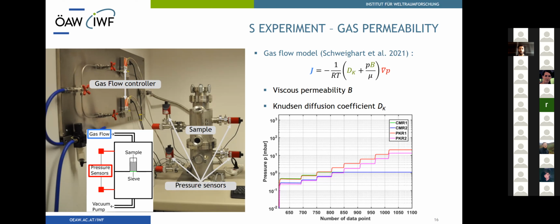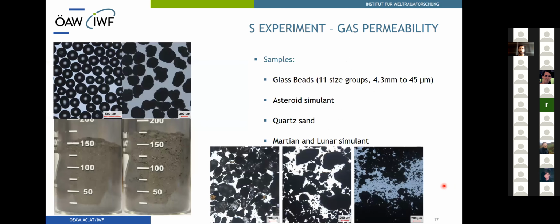In this figure, you can see how we perform the measurements. We increase the gas flow in multiple steps and record the steady state pressures in both compartments with multiple sensors. The main material, which was used to establish a relation between grain size and flow parameters, were glass beads of different diameters, ranging from above 4.3 mm to below 45 micrometers. The top figures show microscope images of glass beads with a diameter range between 355 and 250 micrometers on the left, and between 200 and 125 micrometers on the right. You can clearly see how the smaller beads are not spherical anymore due to the manufacturing process, which is an important aspect to keep in mind.